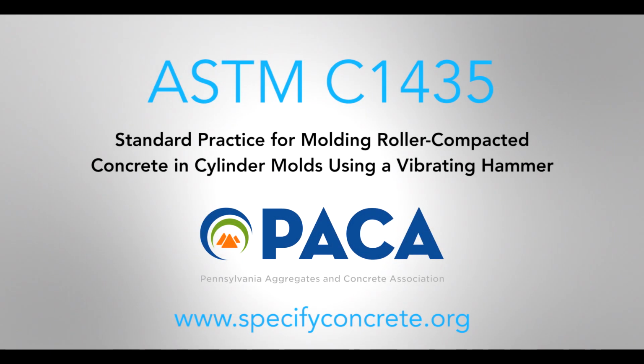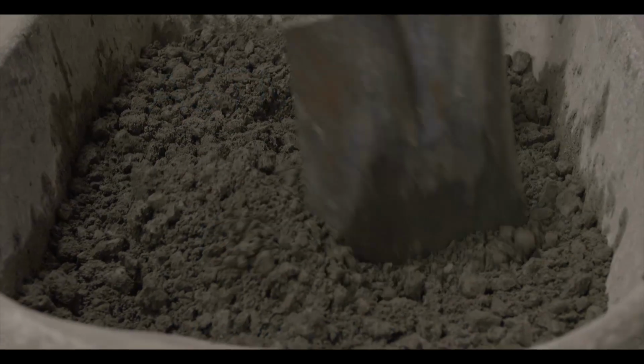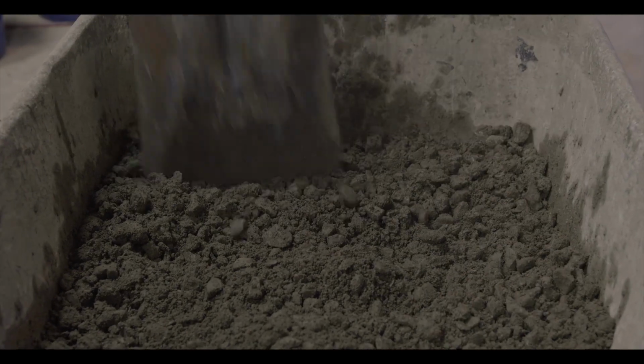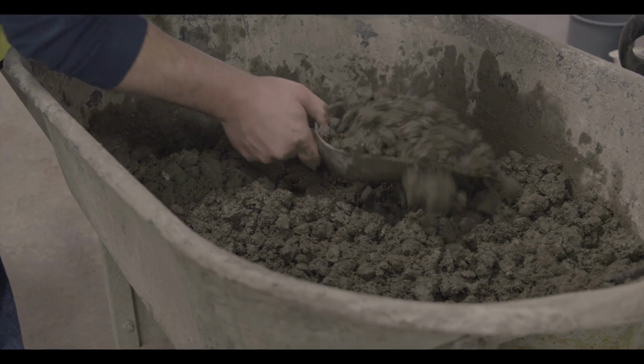This video shows a technician molding strength test specimens in accordance with the ASTM C1435 Standard Practice for molding roller compacted concrete in cylinder molds using a vibrating hammer. Test specimens are molded vertically in cylindrical molds by compacting the stiff to very dry concrete mixture in four lifts